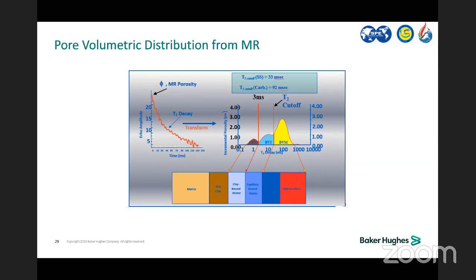The industry uses a standard T2 cutoff of 33 milliseconds for clastics, and 92 for carbonate. But carbonate is a little bit more complex. The standard here in Saudi Aramco is 220. For some formations, after calibration with the core, we reached 340.